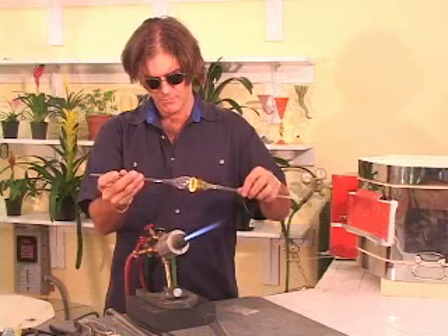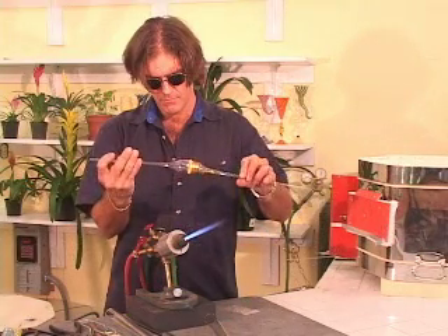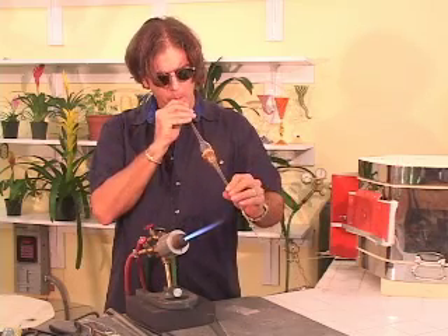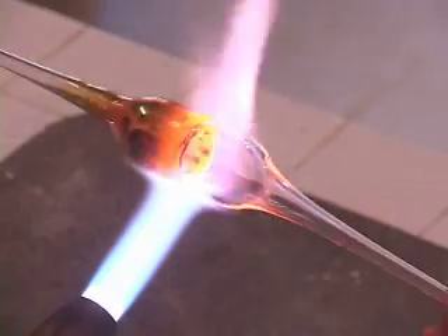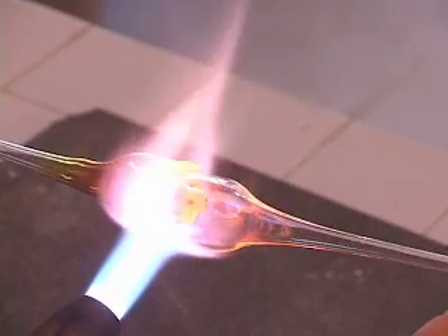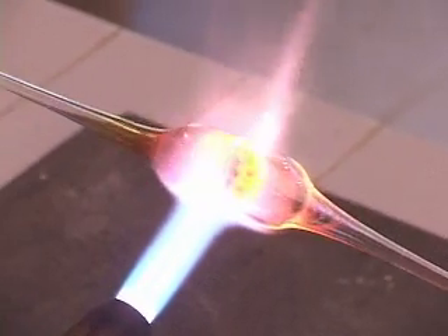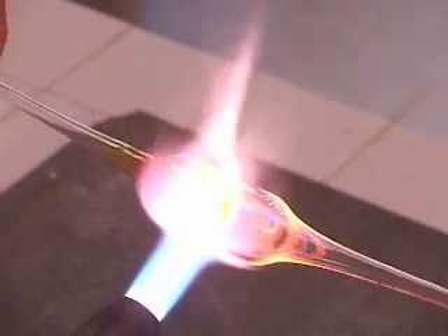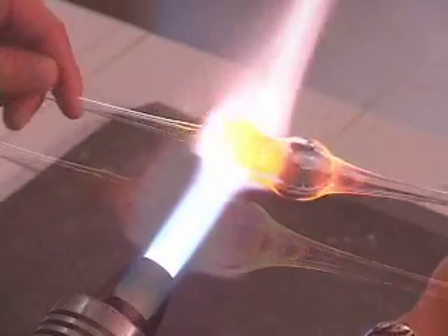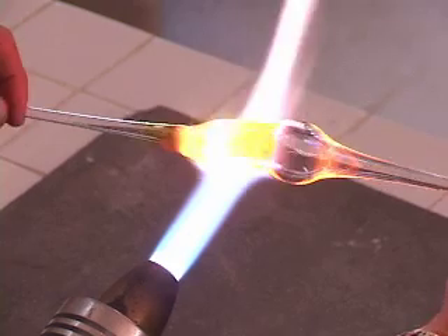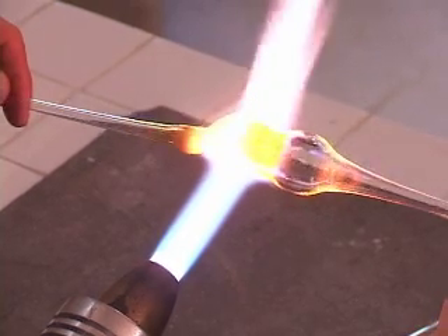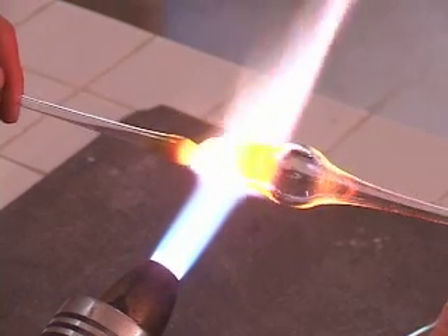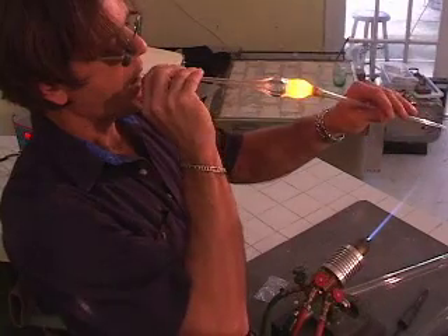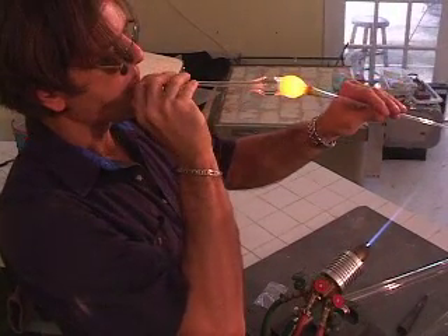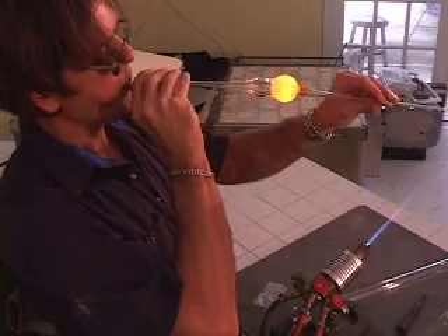Heat both edges until they're molten and join the pieces together. Blow slightly to smooth the inside seal. Reheat the seal to make it smooth. Heat up the entire section and shrink it down, slightly smaller than the original diameter of the tube. Now we'll blow the bead into a bubble and shrink it back down.